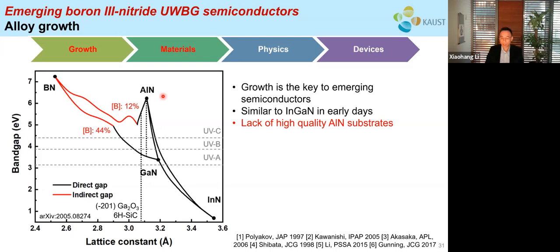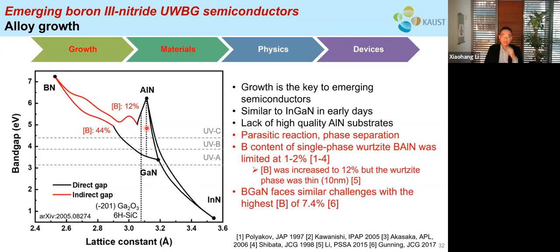So since we talked about the growth of high quality aluminum nitride epitaxial layers, next let's talk about the growth of boron aluminum nitride and boron gallium nitride. Again, it is very similar to that of indium gallium nitride in its early days. They have issues such as parasitic reaction and phase separation. And for a long time, the boron content of single-phase wurtzite boron aluminum nitride was limited at about 1 to 2%, so very low boron compositions. And recently, the boron content was increased to about 12%, but the wurtzite phase was rather thin, only 10 nanometers. Boron gallium nitride faces similar challenges. However, the highest boron content was limited at about 7.4% as well.